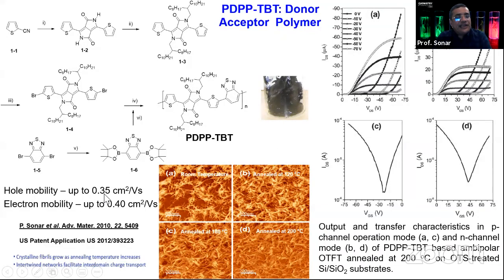And here is a hole mobility calculated in transistor geometry, top contact, bottom gate, having a silicon dioxide as a commercially available substrate. Then we put this polymer thin film on the silicon dioxide after some self-assembled monolayer treatment, and then put source and drain as gold electrodes, completing the transistor. Then, applying a sweeping potential across the gate, we can get a source and drain current.